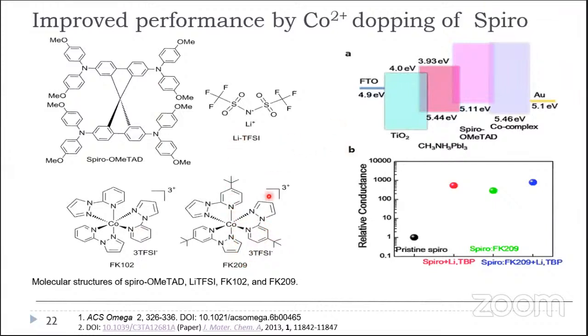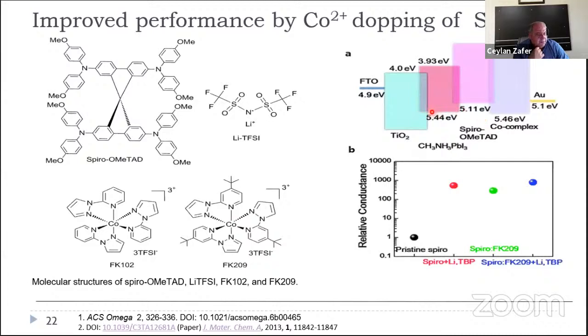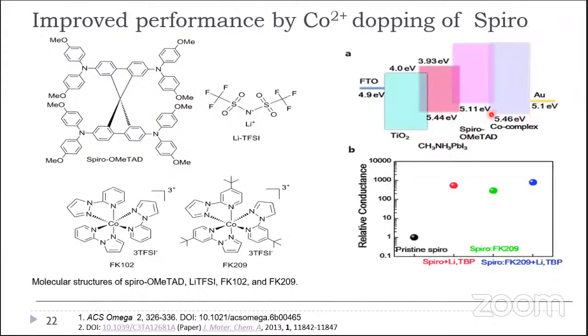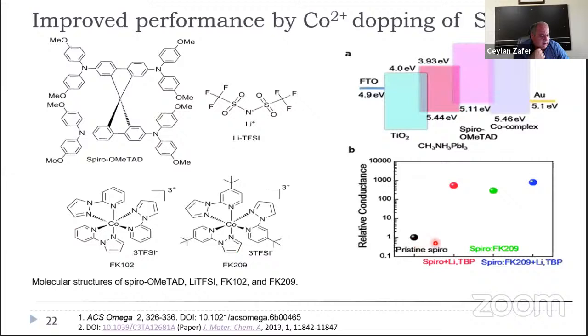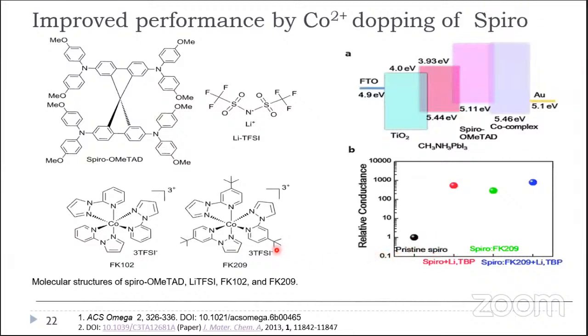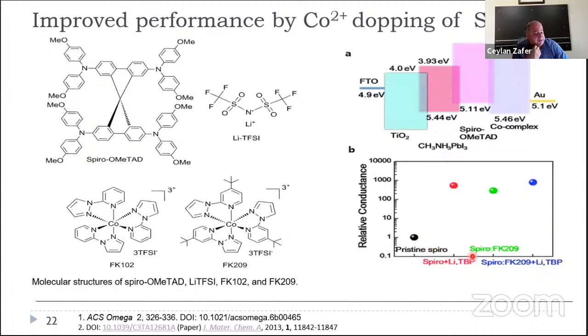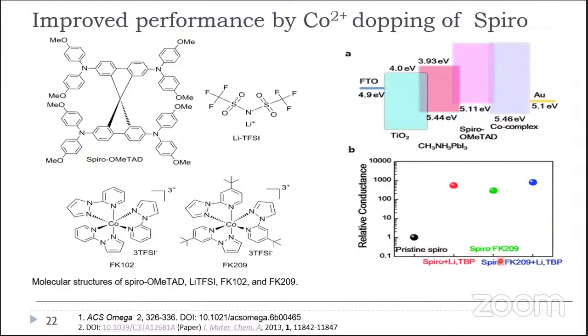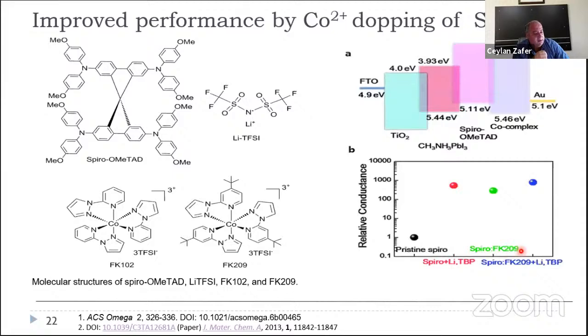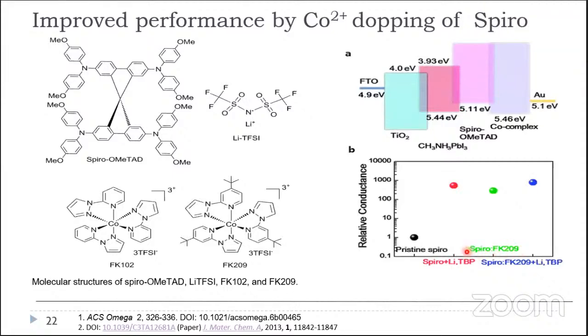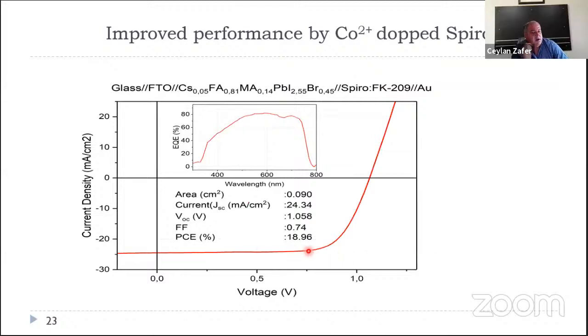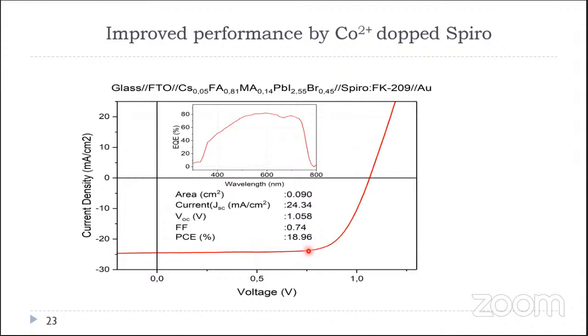And if you see from this energy band diagram, better alignment between the perovskite and the spiro-OMeTAD can be seen upon doping of the spiro-OMeTAD, and the relative conductivity of the spiro-OMeTAD increased drastically upon doping with the FK 209. And what's the effect on the device performance of this? The efficiency improved to nearly 19.